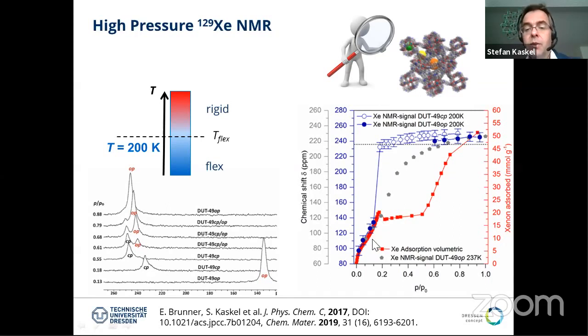And in this diagram, we see the volumetric xenon adsorption isotherm with this strange kink and the breathing behavior. Here we have the transition to the CP phase. So here we go from the OP phase to the CP phase. We have a huge change. Then we go in adsorption to higher pressure. Here we have the coexistence of the CP and the OP phase. And we can even follow the development of two peaks separately. So that's why I'm convinced that the xenon is a great eye for the pore enthusiast and the people investigating the pore systems, because there's a lot of things we can learn from that and get some insights here.